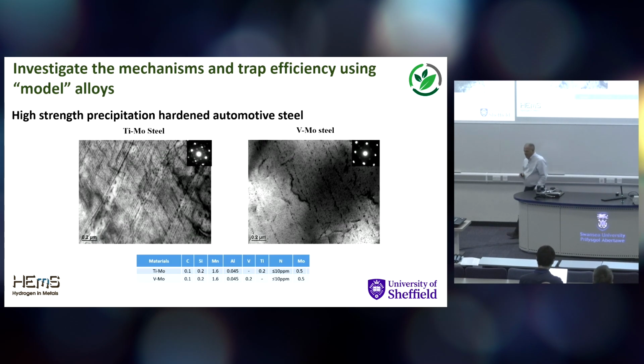So I'm going to run you through some studies that Peng did on what we call the model steel. Of course, there is no such thing as a model steel, but this is high-strength precipitation-hardened automotive steel. It's interphase precipitation, producing very fine titanium carbide or vanadium carbide. In each case, we modified it slightly with a small amount of molybdenum. You can see the compositions down here, quite lean: 0.1 carbon, not much else in there apart from the vanadium and titanium. And in each case, 0.5% of molybdenum.